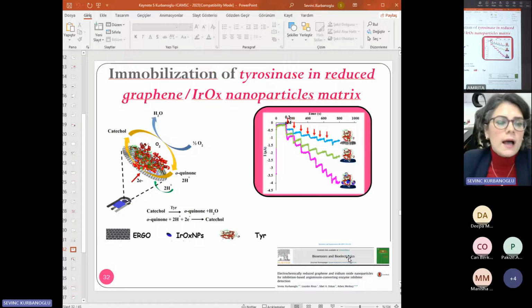And in another study, this time we tried to go one step further, and we tried to modify the surface not with magnetic nanoparticles in this case, but with iridium oxide nanoparticles. We thought we could take advantage of metallic nanoparticles, and we used reduced graphene oxide. For this case, first we electrochemically reduced the graphene oxide, then we added iridium oxide nanoparticles to the system, and again we used the cross-linking method, adding glutaraldehyde here.